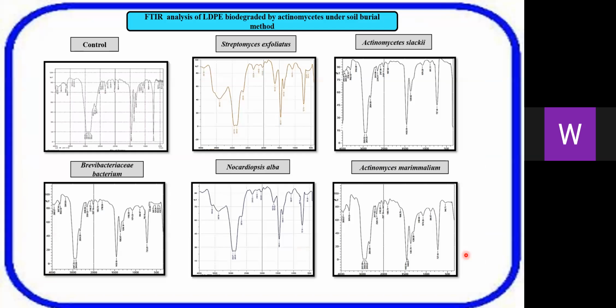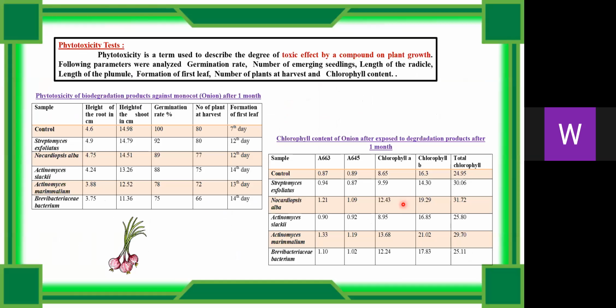This slide shows the FTIR analysis of LDPE degraded by actinomycetes in the soil burial method. Compared to control, you can see the formation of new peaks and the disappearance of some functional groups, observed in all the 5 strains. Phytotoxicity test was done to analyze germination rate, number of seedlings, length of radicle and plumule, etc.,